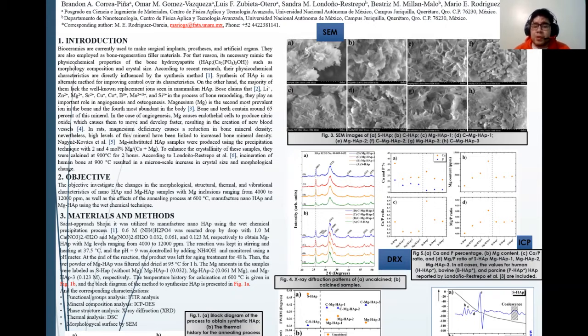Figure 4b shows the patterns for the samples calcined at 600 Celsius degrees, where different lines such as 102, 210, 300, and 202 emerge, which are evidence of recrystallization happening at this temperature.